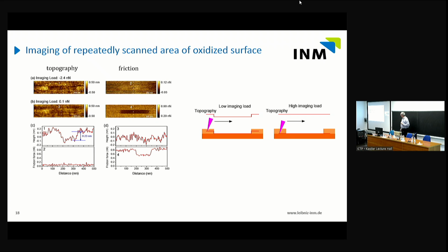So if we image this scanned area, we have a sort of a problem. We scan a little frame here, a little ribbon, if you wish, and then we image the whole result. If you go to extremely low load, you can actually see that the topography is depressed a little bit. This is on the upper left panel. So at very low load, you can see that you scratched away this outer layer, but you don't see anything in friction because we are imaging at zero load. And at zero load, there's zero friction and there's no friction contrast.